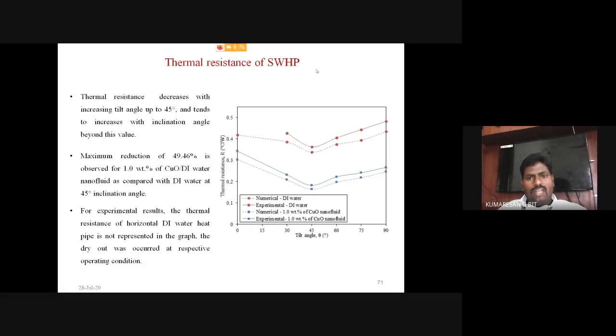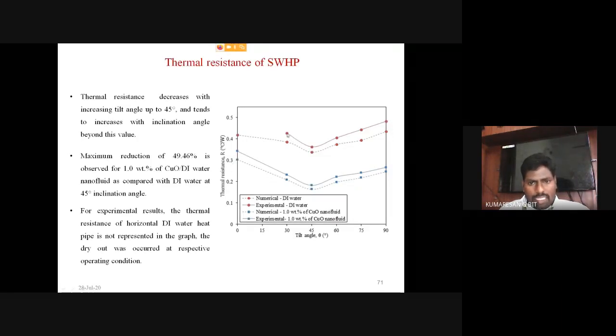Then the thermal resistance of the sintered wick heat pipe, where numerical and experimental results are compared. The heat pipe filled with 1 weight percentage of the copper oxide nanofluid registered the lowest thermal resistance value. And you see here the red color line for the experimental results; the horizontal position is not indicated in the graph. This is because the heat pipe filled with DI water reaches the dry out condition when operating at a 0 degree inclination.